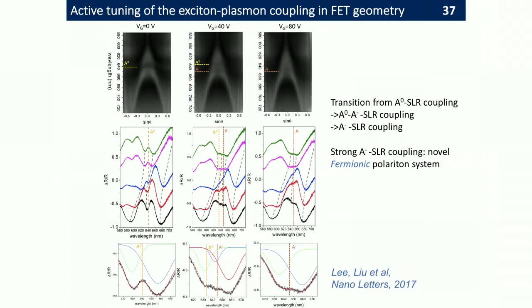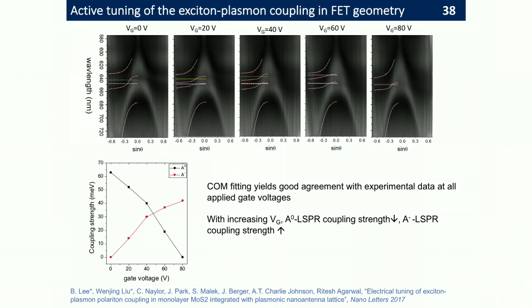And then eventually what happens is as we inject more and more carriers, the strong coupling for the free exciton transitions to weak coupling. We don't see this anti-crossing behavior, but we only see strong coupling with the trion. So this basically means we can tune the system in a dynamic manner. And so these are more spectral details, which I won't bother you with. So the entire story is basically summarized here.